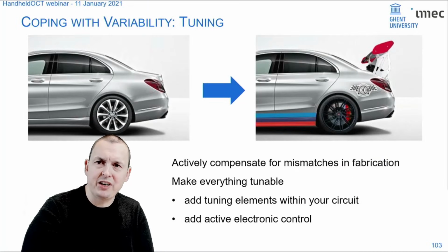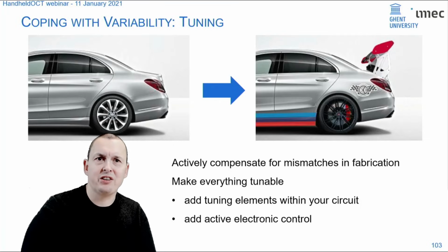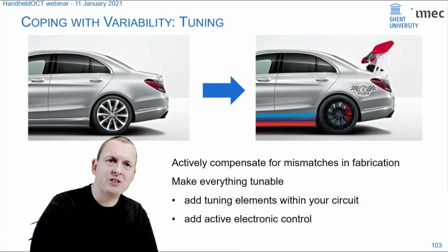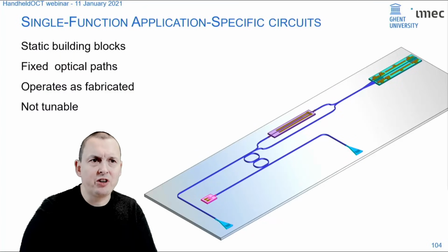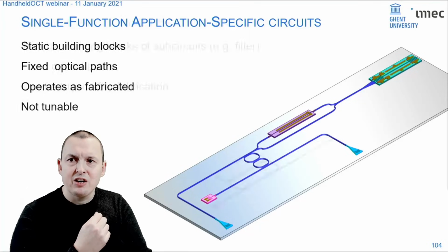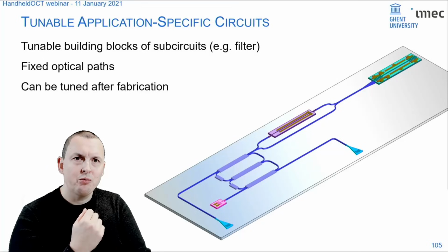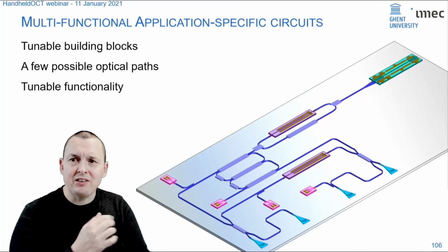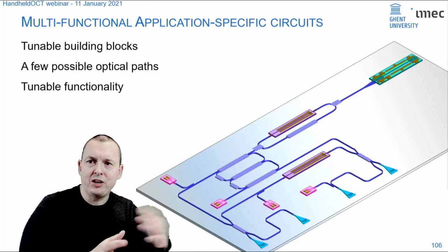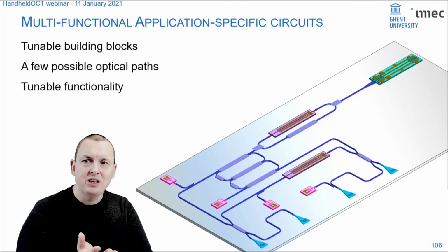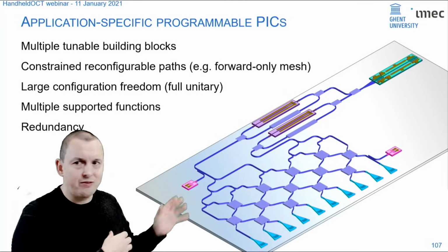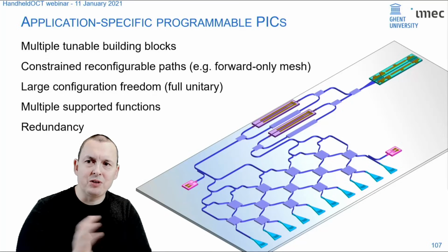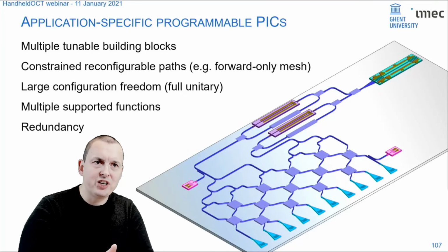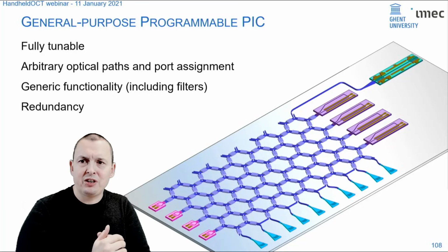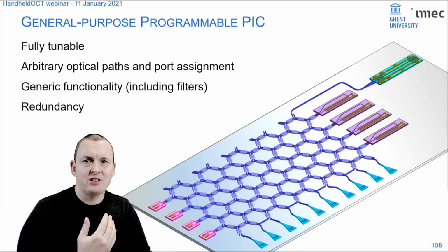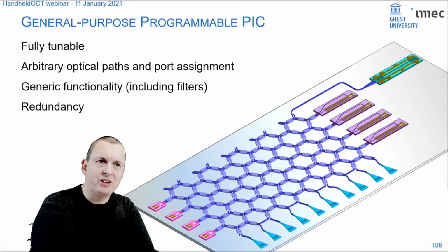So the last technique to cope with variability is tuning. You can actually start compensating and improving and optimizing all the elements in a photonic circuit dynamically. So instead of building a circuit like this, where essentially all the elements are fixed, you can now, for instance, replace the filter, which is the most sensitive part, with a tunable filter, where all the elements are tunable. And that opens up a whole avenue to making circuits that can actually be reconfigured or slightly modified to do multiple functions. And what we're seeing today are circuits like this, called a multiport interferometer, which can be reconfigured to do different types of operations, or, one step further, can operate as a multifunctional processor that can process not just optical data, but also electrical data.